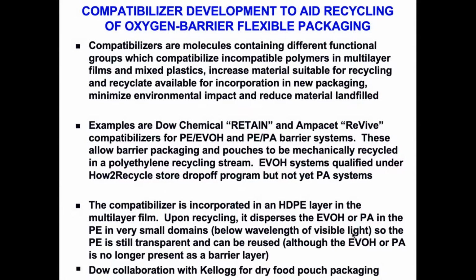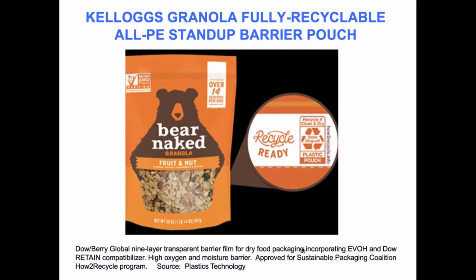The compatibilizer is incorporated in a high-density polyethylene layer, and when the material is recycled and the polymers are melted, it disperses the ethylene vinyl alcohol, or if there's a polyamide layer in there, in very small domains, smaller than the wavelength of visible light, so that the polyethylene is still transparent and it can be reused. Although of course the ethylene vinyl alcohol or PA layers are no longer present as layers. And Dow's collaborated with Kellogg on this for dry food packaging. Here's an example of a Kellogg's granola, fully recyclable, all PE stand-up barrier pouch. So a 9-layer structure, incorporating EVOH and Retain compatibilizer with high oxygen and moisture barrier, and approved for How to Recycle.